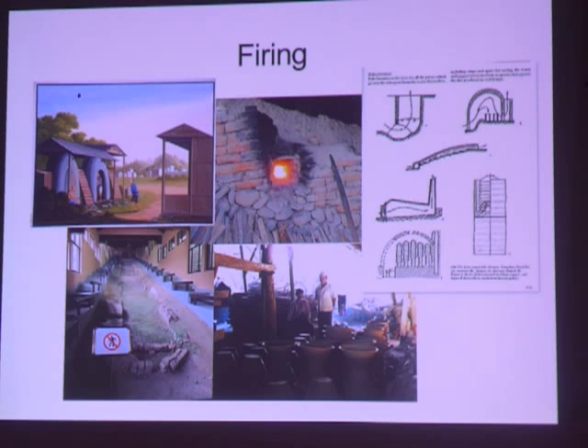In some cases, the prepared ceramics were placed in containers called kiln furniture, or saggars, according to their size, and put in the kiln. The big ones were placed in the middle of the kiln and the small ones at both side ends. Since the temperature is higher and stable in the middle, it is much easier for making large wares, and the temperature is lower at both ends, so the small wares were fired there. Generally, the temperature in the kiln was kept between 1200 and 1300 degrees Celsius. The final glaze depends on the cooling method, composition of gases in the kiln, and their density.